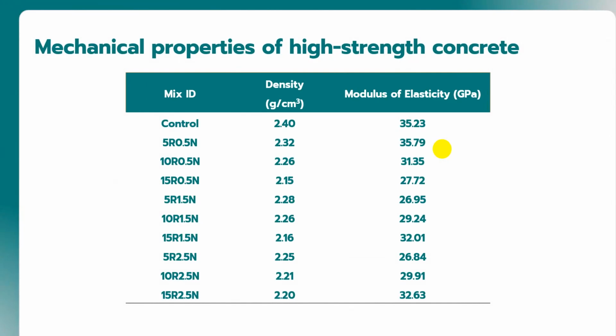For the 0.5% NRL, we found that when we add more RDF, the modulus of elasticity is reduced. But for NRL 1.5% and NRL 2.5%, we found that if we add more RDF, the modulus of elasticity increases. But for the density, whether we have 0.5% NRL, 1.5% NRL, or 2.5% NRL, if we add more RDF, the density of the concrete is reduced.